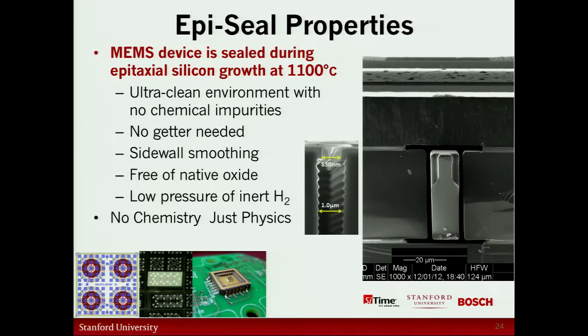A lot of really good things happen when you cook something at 1100 degrees C for an hour in terms of killing the chemistry. One thing in particular, if you have hydrogen gas in an environment at that temperature and exposed silicon sidewalls, the hydrogen promotes a smoothing process that takes away what was originally the scalloped sidewalls of the etch process and replaces that with something that's almost atomically smooth. What's important there is that later on, there's no roughness or sort of unpleasant surfaces that are going to relax and age over time. The surfaces of this micromechanical element are basically in their ground state, and there won't be any further evolution in the structure. That leads to some of the really important benefits for aging.